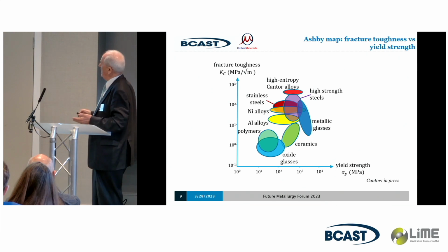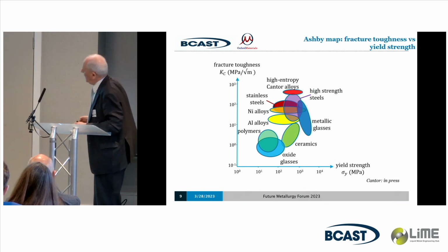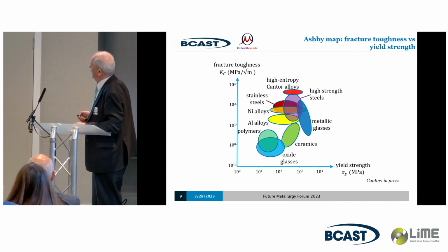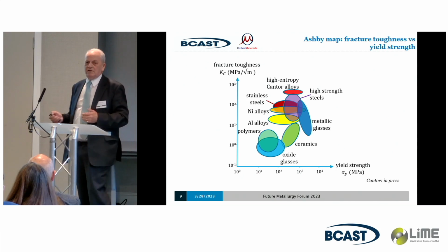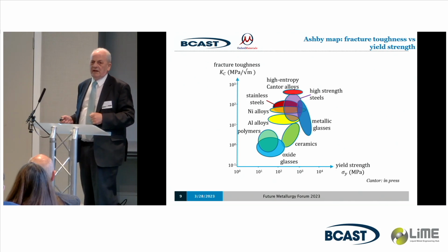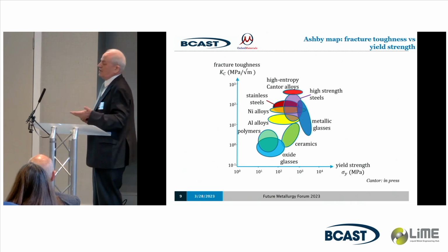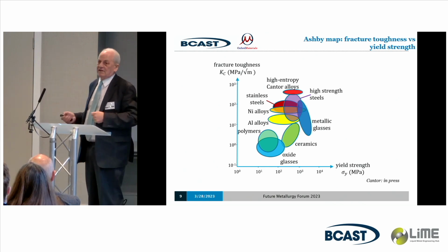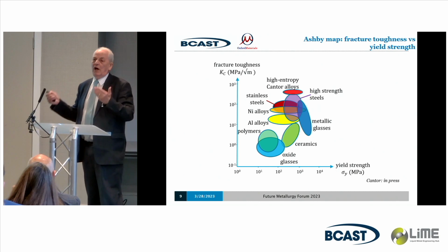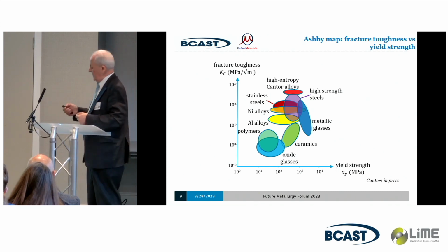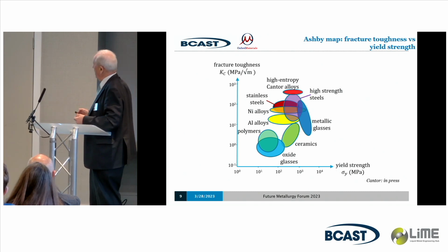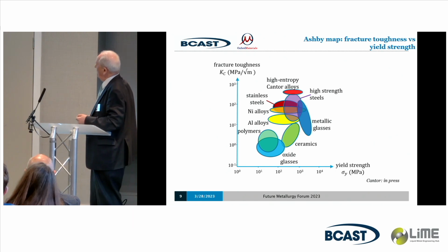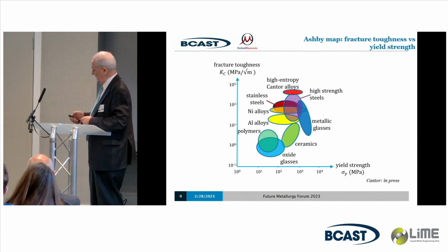This is an Ashby map. There's the fracture toughness. I think you were talking about 70 something, Harry, which is here. They have between 200 and 300 megapascal root meters fracture toughness, and that's with 100% ductility, very much the softness of pure copper, like any single phase FCC material. On the other hand, they have the strength, not far off, of the best high strength steels. Not quite as good as the best high strength steels, which are higher.